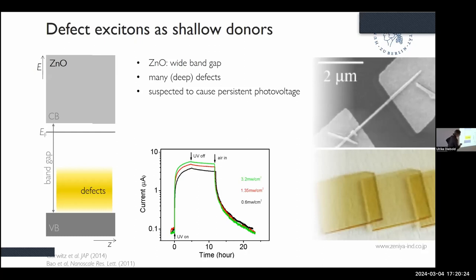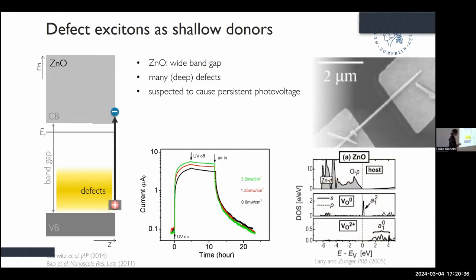And the conductivity goes down again when you expose this wire to air. And the reason for it is likely the oxygen in the air that is filling oxygen vacancies. There are theoretical calculations already 20 years old. Here you see that at the top of the valence band, you have these oxygen vacancy states. And then when you ionize these oxygen vacancies, you generate density of states in the region of the Fermi energy. Yeah. So the photo excitation creates states in the region of the Fermi energy where the conduction happens. So this is one paper supporting the hypothesis that the persistent photoconductivity goes back to oxygen vacancies in zinc oxide.